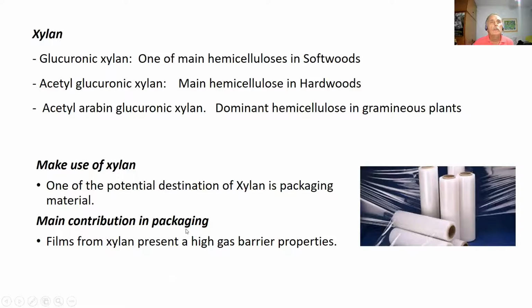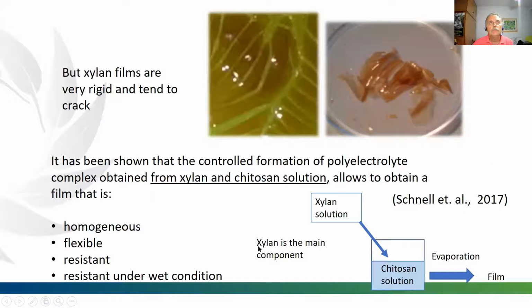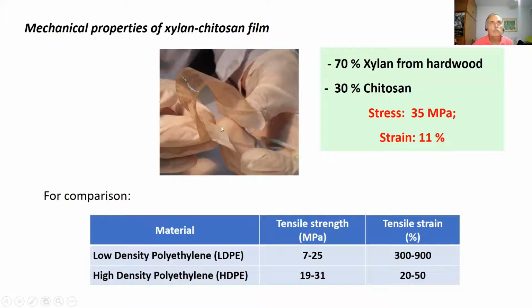Why? Because films from xylan present a high gas barrier property. But xylan films are very rigid and have a tendency to crack, as we can see in the photograph. It has been shown that the controlled formation of polyelectrolyte complexes obtained from xylan and chitosan solutions allowed us to obtain a film that is homogeneous, flexible, resistant, and also resistant under wet conditions, by considering the addition of xylan solution and chitosan solution. The film is flexible, as can be seen here.